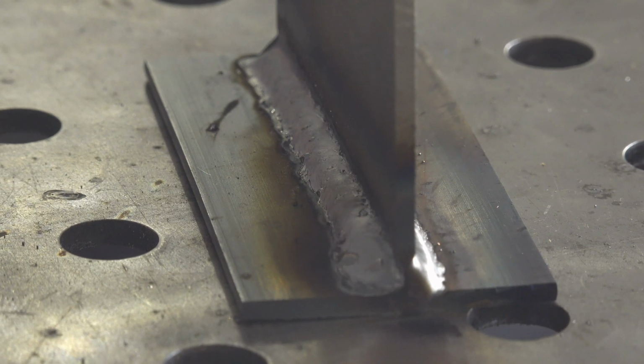Sometimes, especially in dual pulse mode, it would just stutter if I had too long of a stick out. If I ran a shorter stick out, it ran much more reliably. At higher amperages, it was less picky, but it still seemed like the voltage was on the upper end of too high. I'll have to do some more experimenting at some point.